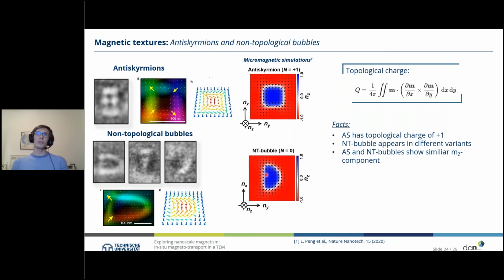Describing the textures now a bit more in detail, which we see in our experiment on the manganese platinum tin sample. One is the so-called anti-skyrmion, which has this square-like structure, which you can see here in the LTEM image, where if we look at the magnetization of that feature, which is shown here on the right-hand side, it also has this square-like structure with the field going in, going out, here going in and going out again.